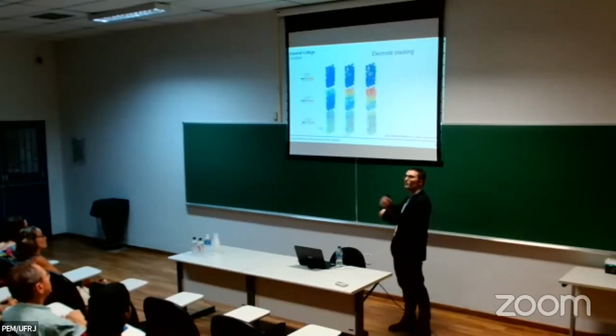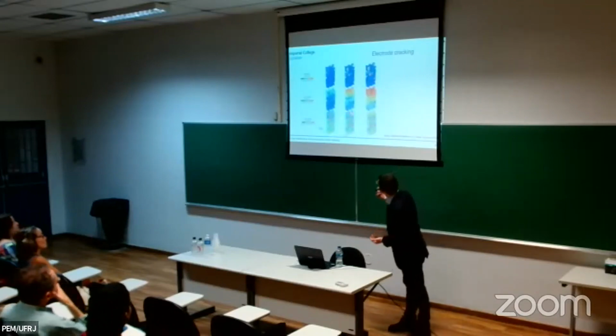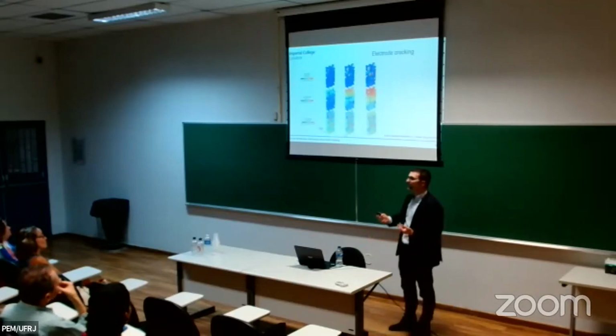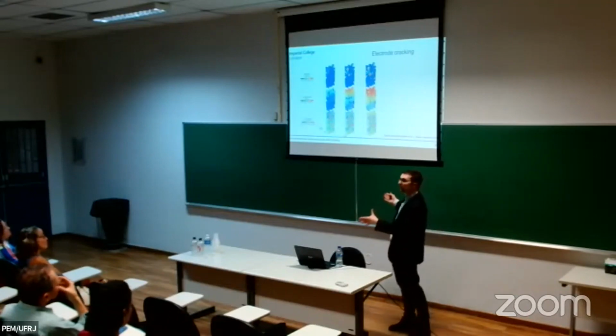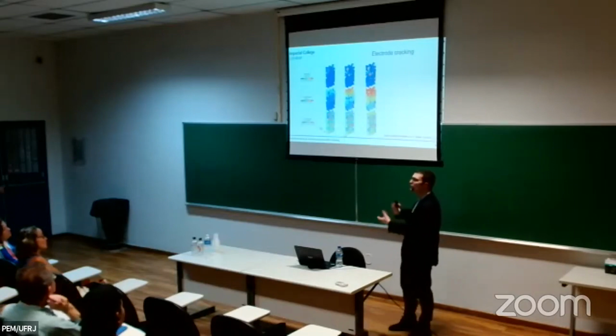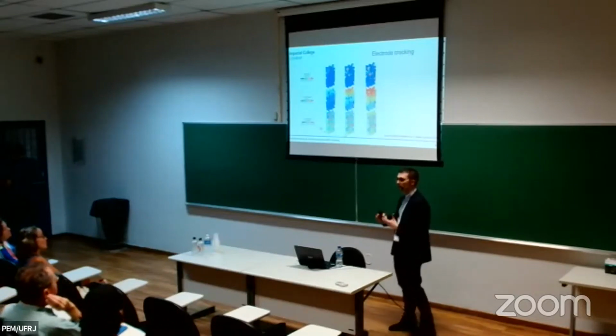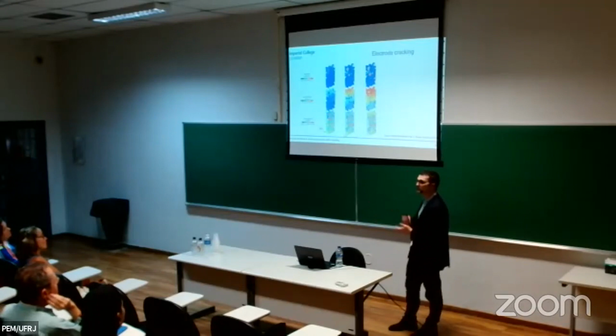We can see the distribution of lithium, and the distribution of cracks, where cracks are appearing. And we see a very heterogeneous electrochemical response. So we can see that, first, the thickness of the electrode plays a big role, but we may also want to look for solutions that do not involve a homogeneous distribution of particles. You can get very different responses within the electrode.